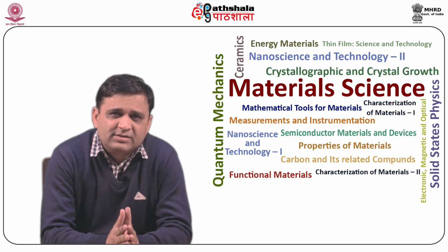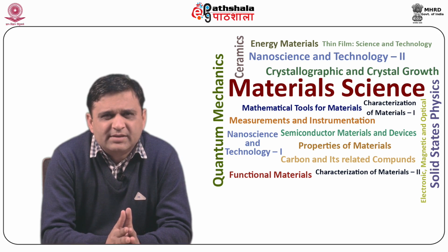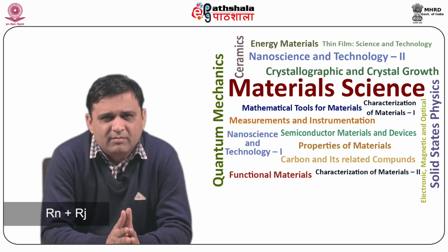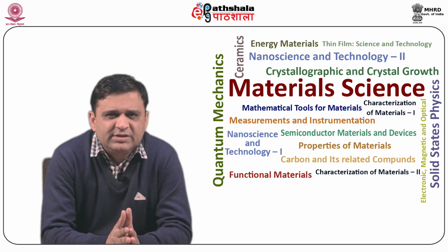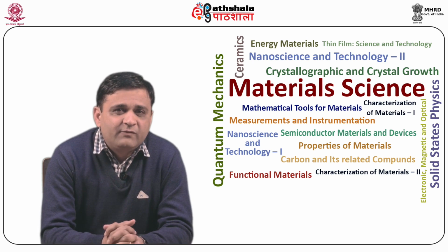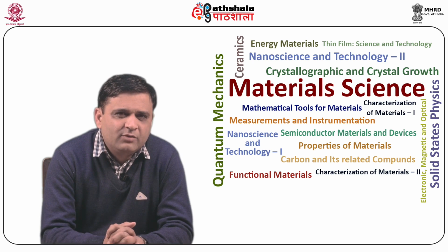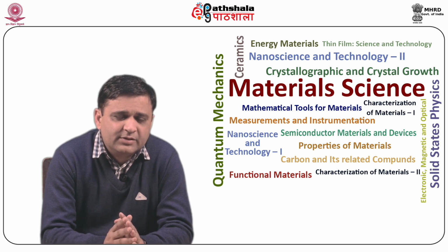If Rn are the lattice vectors that define the lattice, and Rj the position of the atoms with respect to any one particular lattice site, then the position of any atom in the crystal is given by Rn plus Rj, as you can see in the diagram. It follows that the scattering amplitude for the crystal factorizes into the product of two terms which are written below here. Here Fj is an atomic form factor once again, and Q·Rj is a phase factor.